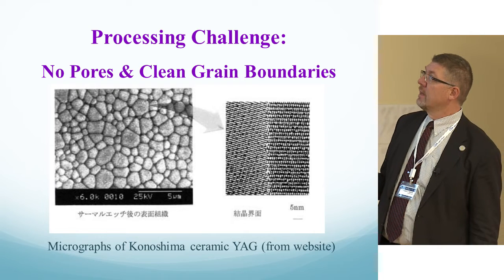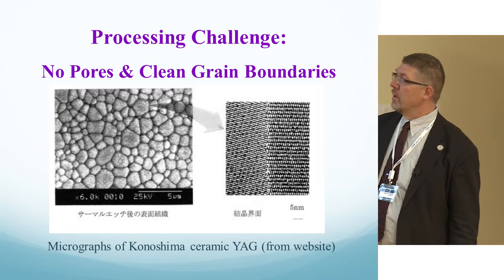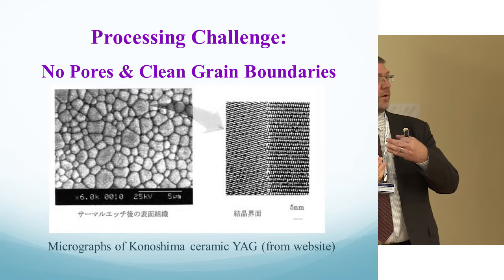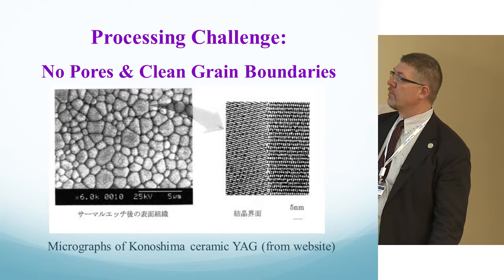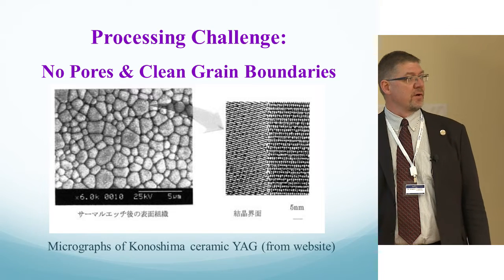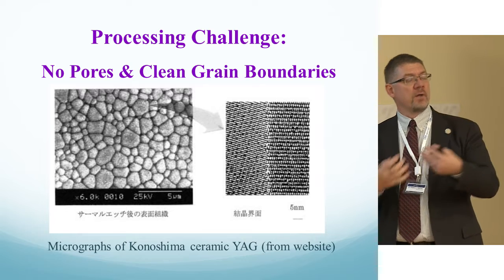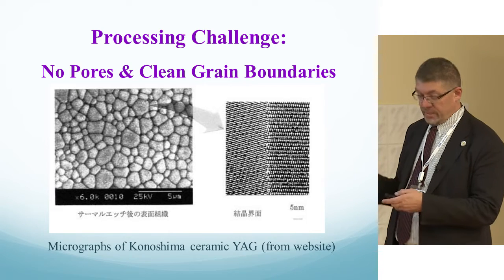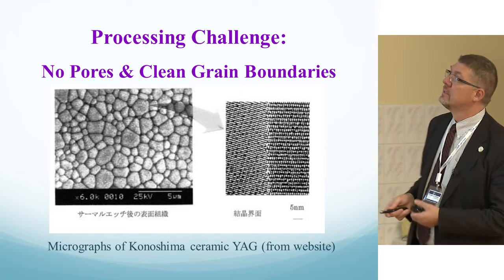They've also done a grain boundary here where they've tried, on purpose, to move the material, and you can see that all of the boundaries line right back up again after they go to the interface. They're trying to show that their processing allows them to do this, and I'll show more on this in just a minute.